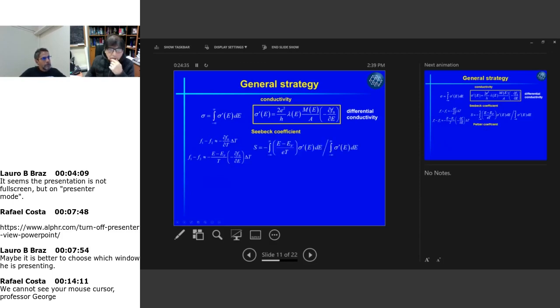This way I can write the Seebeck coefficient through this equation here, which is very similar to the equation for the conductivity. It's an integral of the differential conductivity as for the conductivity, but it's weighted by this E minus EF over the charge of the electron and temperature. And I have to divide by the total conductivity. Remember that the Seebeck coefficient was multiplied by sigma in that equation that I showed you. So I can play the same game as I did to obtain the Seebeck coefficient and gain again the sigma prime and have an integral that is going to be very similar to that. But as we know, the Peltier coefficient is equal to temperature times the Seebeck coefficient.